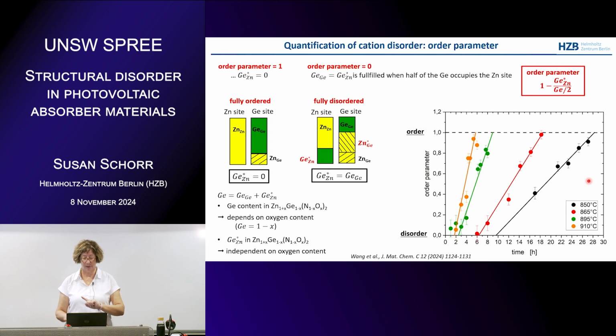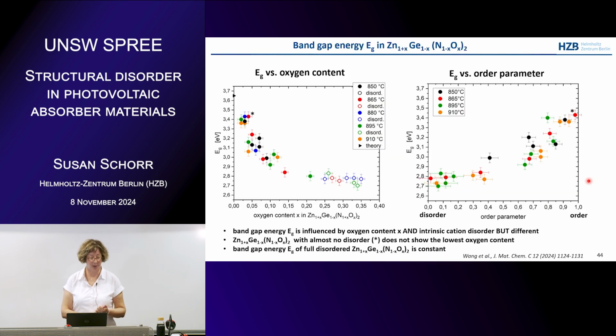So now we know that we can tune the disorder by the reaction conditions. The question is, what has happened with the band gap? This is the band gap versus the oxygen content, and on the right side you see the band gap versus the order parameter. So here is the order parameter. You see that the band gap is influenced from both, from the oxygen content and from the disorder, the cation disorder, but somehow in a different way.